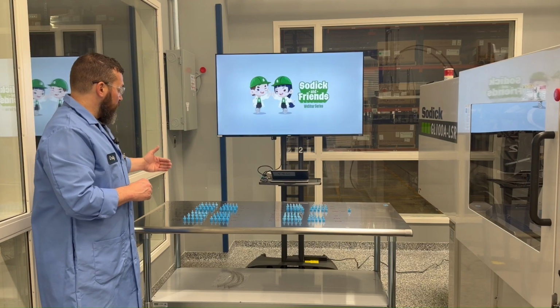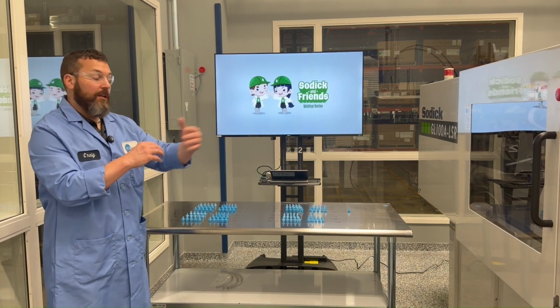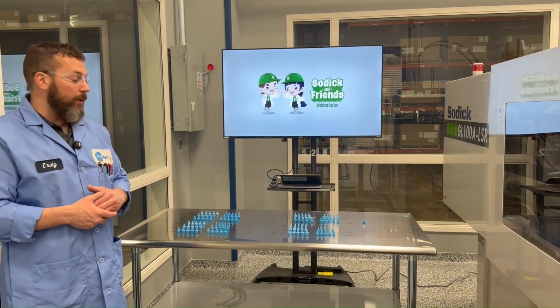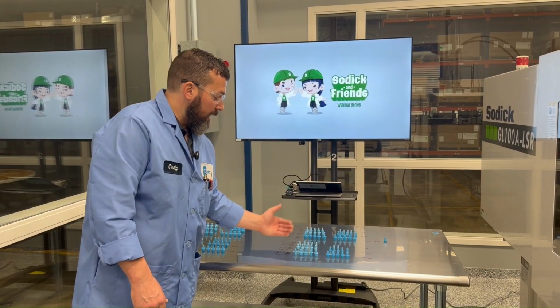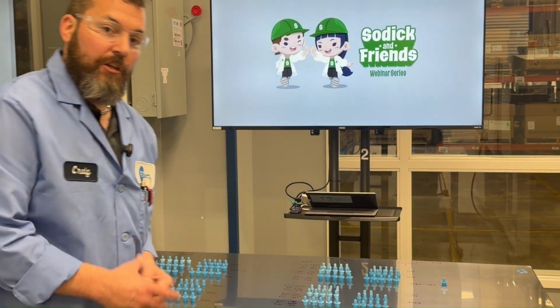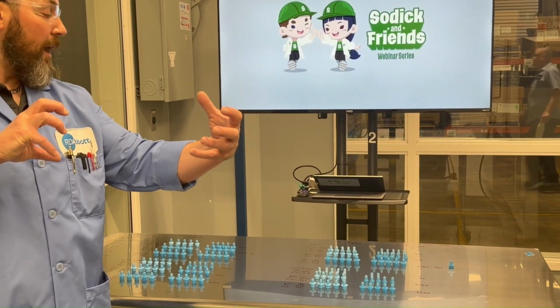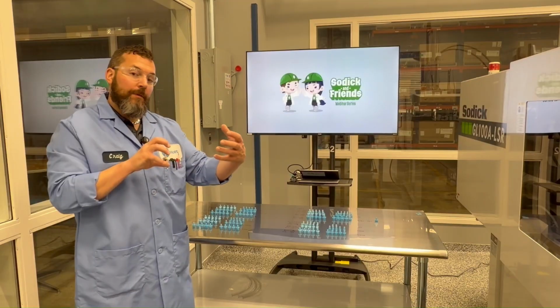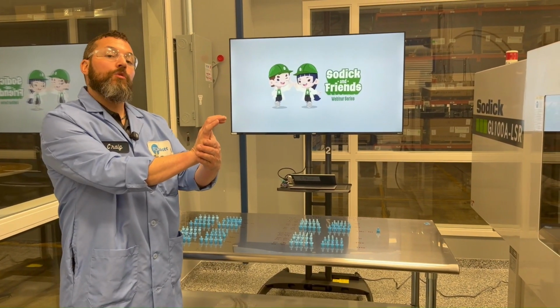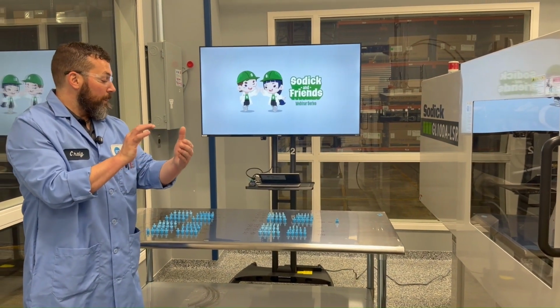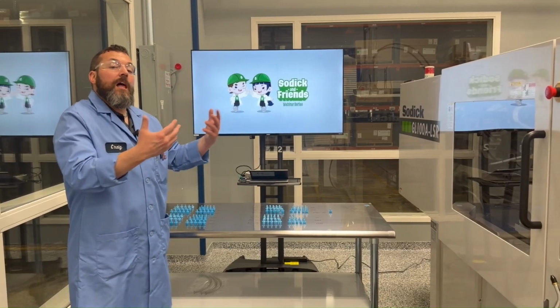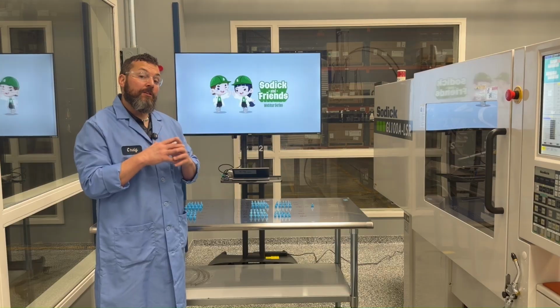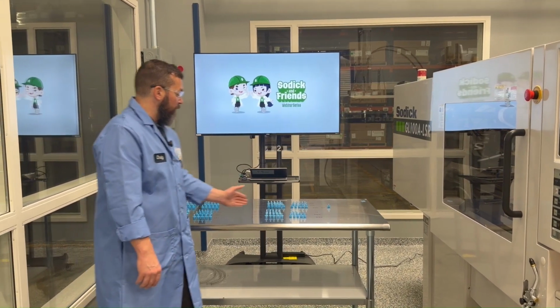So again, with a system set up for vacuum, also when we panned over to look at the parts, we can see some of these parts have a lot of air, and the different fill between vacuum and no vacuum, that vacuum is pulling all atmosphere out of the cavity. So with no atmosphere in there, we have less pressure in the tool, in that cavity that we're injecting against. So the problem is, as we are volatilizing our cyclics off from the material into the tool, that vacuum is pulling them out, but it's also ripping the material through the tool. So this could hinder a balance. And this is, again, why I ran 2 different iterations, vacuum and then without vacuum, so we could see how this fill is.